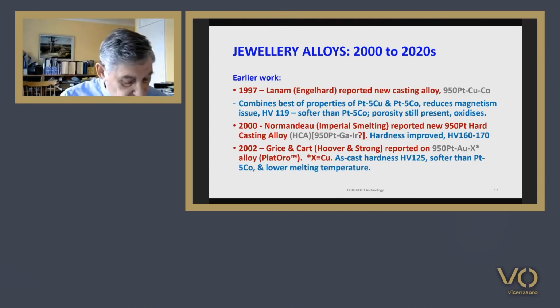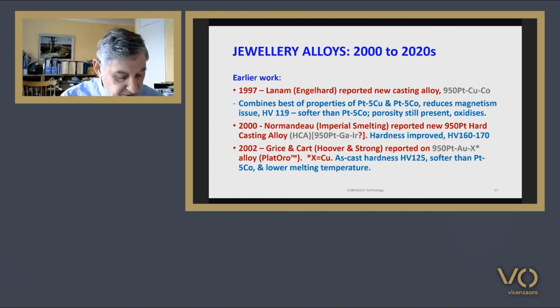Lanham of Engelhard, in a paper presented at the Platinum Day Symposium in New York, reported on a new investment casting alloy, 950 platinum copper cobalt, that combines the good properties of the platinum 5% cobalt alloy and the 5% copper alloys, and reduces the issue of magnetism in platinum cobalt alloy. Its as-cast hardness is about 119 Vickers, a little lower than the platinum 5% cobalt alloy. Porosity is still present, and it had a tendency to form a surface oxide on heating.